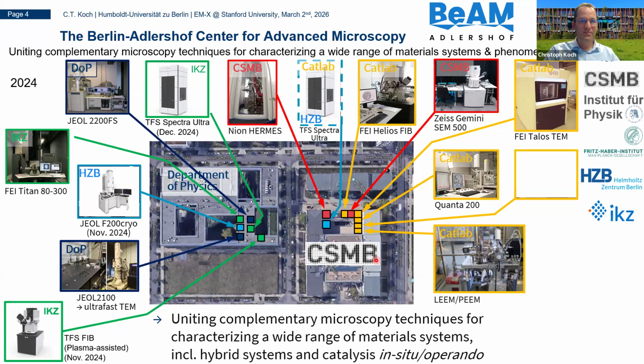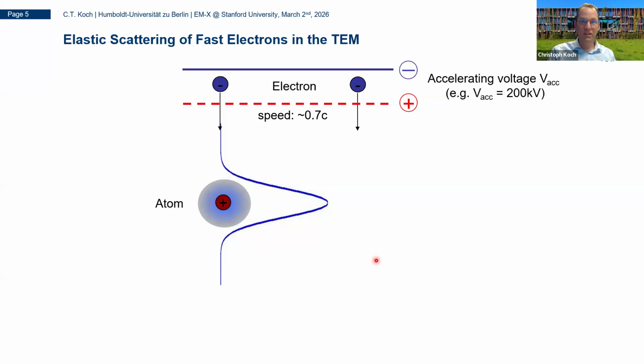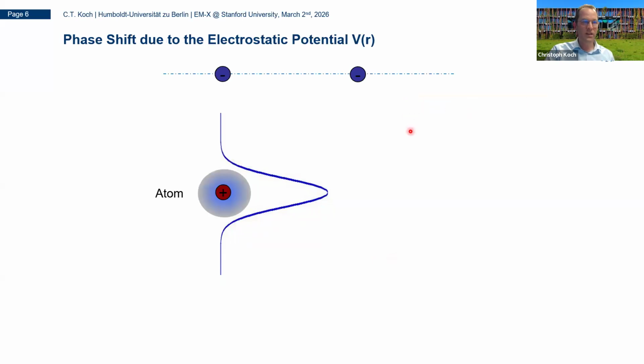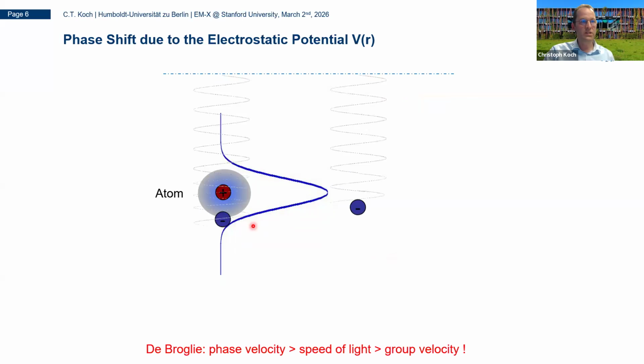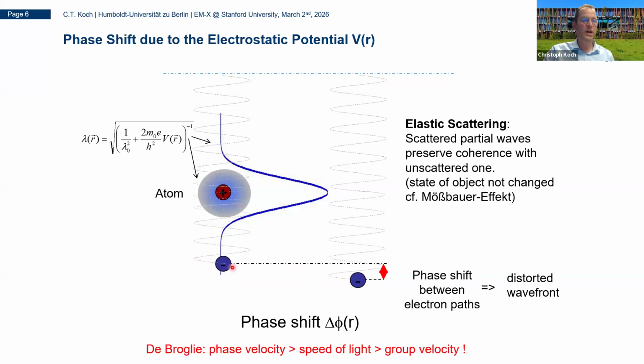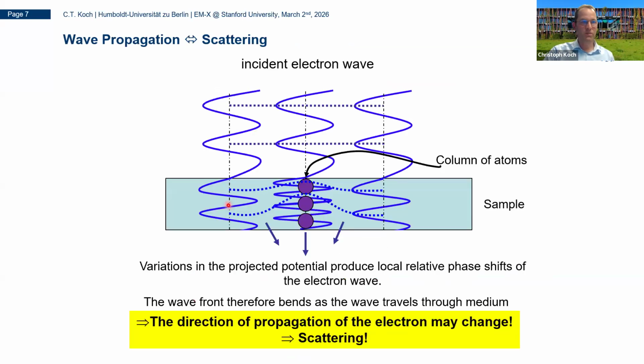I won't go into all of this, but limit myself to imaging the phase that electrons experience when they scatter through materials. So when we accelerate electrons, for example, using a 200 kV electron microscope, they have quite a short wavelength, and they travel at like 70% of the speed of light. But when they then see the positive potential in the material, for example, this atom here, the wavelength shortens. And that means when they arrive on the detector, there's a phase difference between parts of the electron wave. So it's always only one electron, even though I put two blue dots here. Parts of the electron wave that have traveled through vacuum or a different part of the sample and this atom here. And this phase shift allows you then to know that there is an atom and also recover what the Z number, for example, of this atom is.